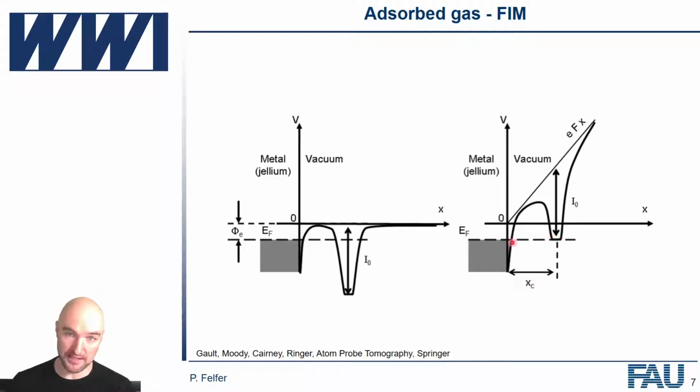And obviously there's a certain tunneling probability. You've probably all had some physics courses and know that the tunneling probability also goes down exponentially with the distance. And we have some tunneling probability, and we need to increase the field up to a point where this is happening. And this also means it can't happen very, very close to the atom because the field would need to be very, very high for it to happen very close to the atom. So it's kind of a trade-off between the tunneling probability that we get from having a distance here and the field that I need